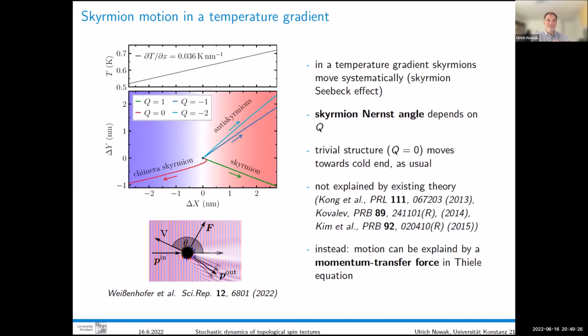All of them move. So that is the first thing we can say. So skyrmions in a temperature gradient move systematically. So in addition to the Brownian motion, we have also a motion in some direction. One could call that the Skyrmion-Seebeck effect; motion of particles in a temperature gradient for electrons is called the Seebeck effect. So we could call that Skyrmion-Seebeck effect. But there's also some angle, so they don't move just to the right or just to the left, but under some angle. And if there is a perpendicular component in the temperature gradient, that is called Nernst effect. It exists also electronically or for spin. It's also spin Nernst effect. So this could be called the skyrmion Nernst effect.